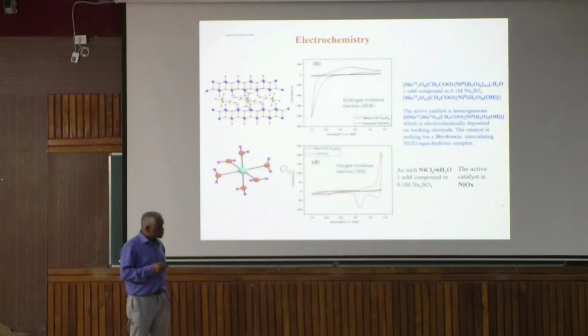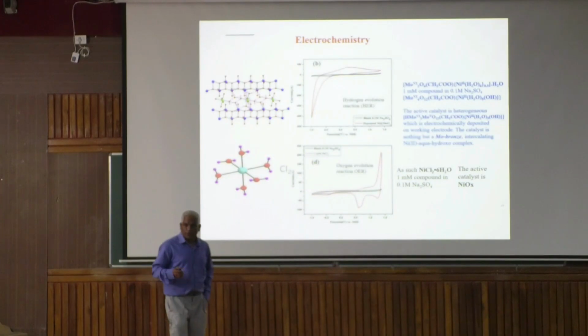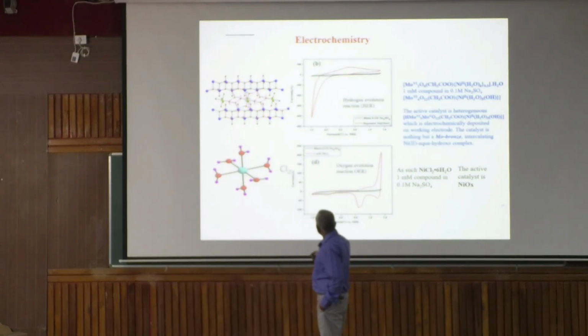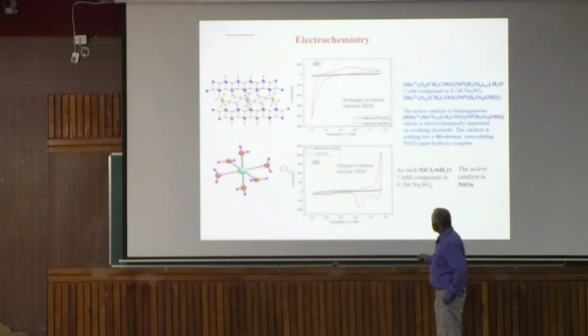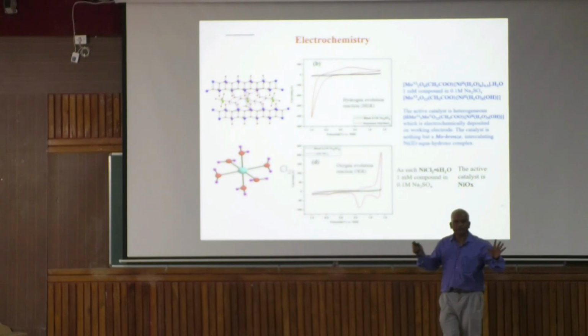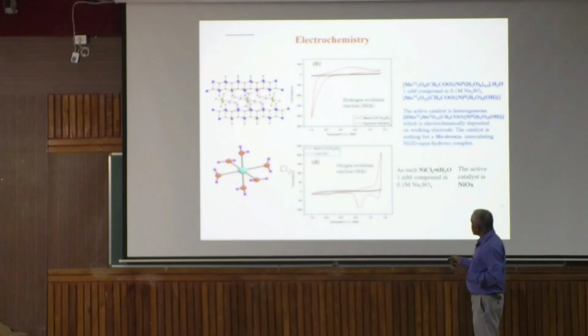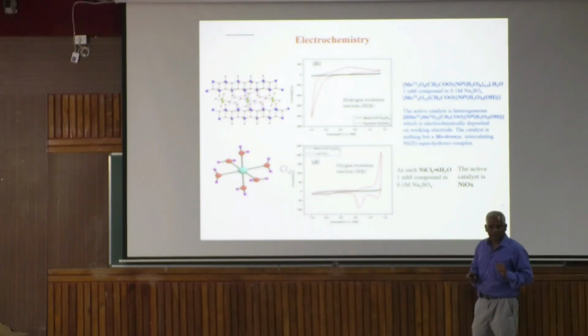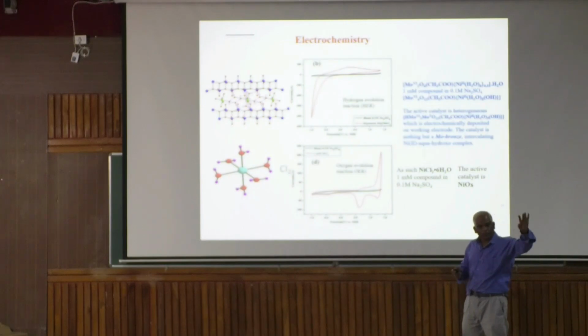What is the story? I told you nickel aqua compound you can get easily from your bottle, from your lab, because it is nothing but nickel chloride, NiCl2·6H2O, this compound only. This compound, if you take CV, you get this red feature, and after some time you get deposition. It is water soluble. But if you do electrochemistry for several cycles, you get deposition on the electrode and this gives water oxidation. After some time, oxidation stops because those particles agglomerate, then no catalysis. Nickel chloride, if you oxidize in water, homogeneous solution, you get electrodeposition of nickel oxide. It gives water oxidation. That means nickel goes to nickel 3 plus state, 4 state, then gives water oxidation.